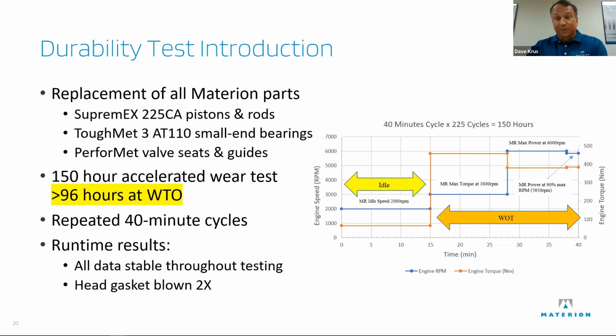I've got 350 slides of data if anybody wants to see them, but they all look like these curves that run straight across and nothing really happens, aside from the two times they blew the head gasket. And you can see some pressure drop when that happens, as you would imagine. That's an indication that we were running the engine really hard, of course. The first time it blew, they were able to resurface the block. The second time, fortunately, it was near the end of the test. There wasn't enough stock left on the block to resurface it, so they just lowered the pressure and limped through the final hours of the testing.